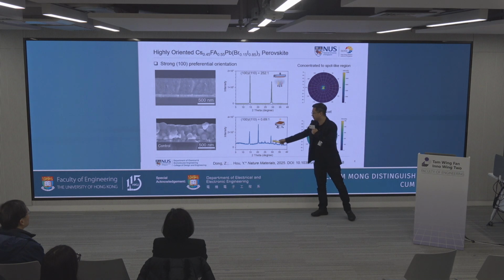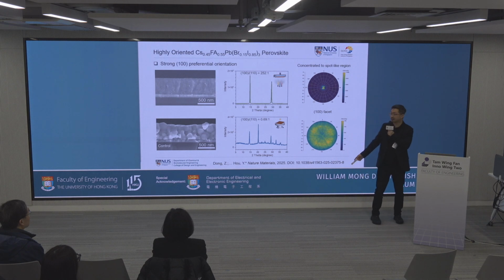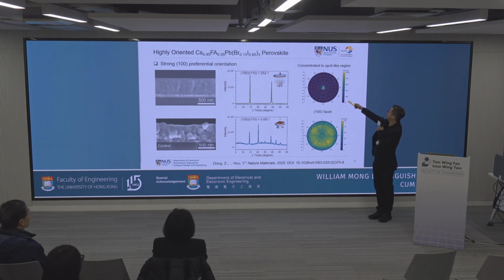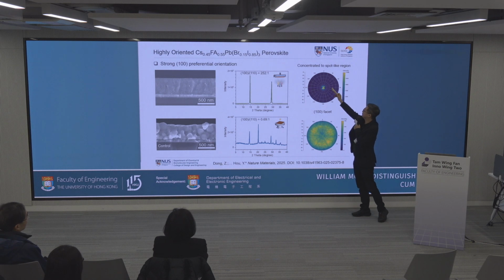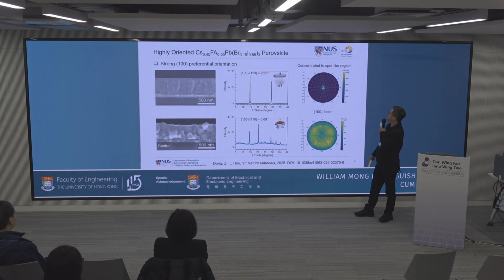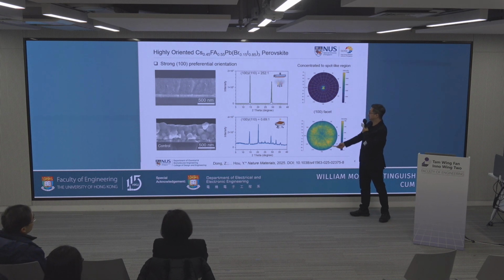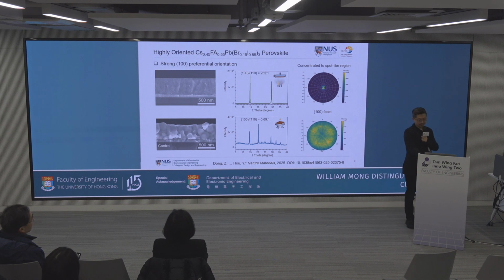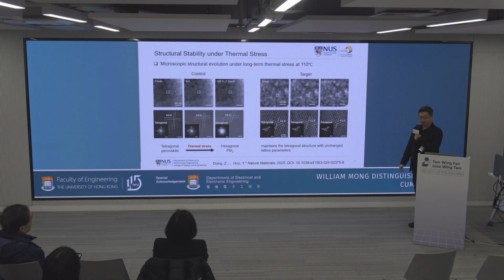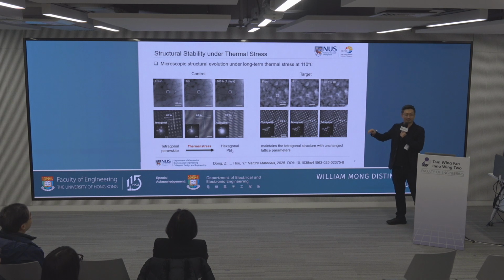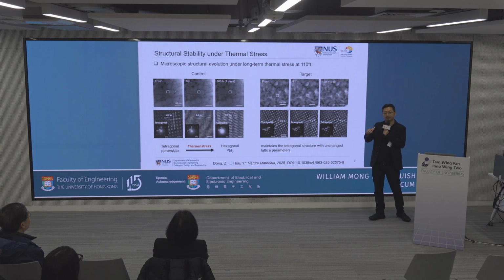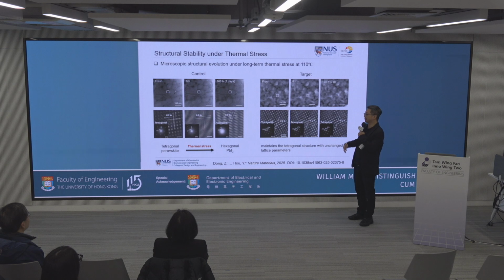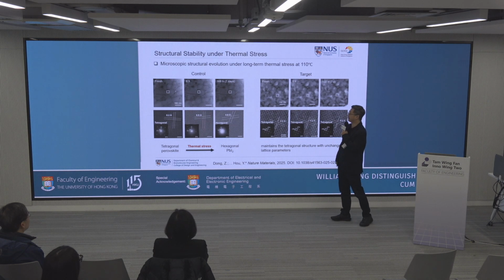And if you now look at this normal solution process one, you see many different orientations. If you look at the pole figures, you can see the dramatic contrast. All this oriented perovskite is centralized here in the center, but the solution process one has different orientations, so it's different directions. I don't want to say this is a single crystal. Obviously, this is not a single crystal. This is polycrystalline, but the film quality is very high and shows some behavior close to the single crystal, but it's definitely not a single crystal.